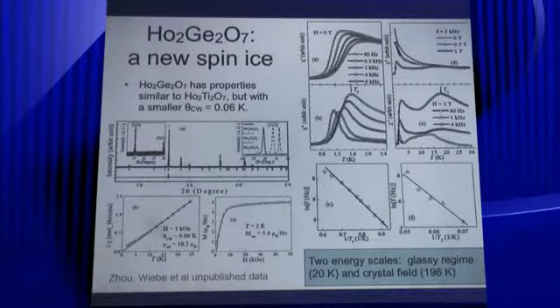And we've done AC susceptibility measurements down to low temperatures in this compound. It actually looks very similar to holmium titanate. So it has these two features, a peak around 1 Kelvin or so, and then another peak around 15. And if you track their temperature dependencies, you can extract 2 energy scales. One of these is the crystal field regime, 196. And the other is a so-called glassy regime around 20 that they found for holmium titanate as well.